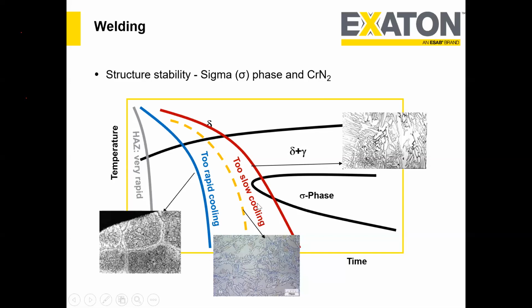For duplex stainless steel, we need to optimize the cooling rate in such a way that it neither intersects the C curves, which form the undesired sigma phase or chi phase, nor cools so fast that it forms chromium nitride. If it forms chromium nitride, see the problem: we are depleting the chromium and also the nitrogen, so our effective pitting resistance is depleting. Hence, that area is a potential site for pitting attack. The sigma phase is exactly the same thing. It is extremely hard, brittle in nature, and a potential site for pitting corrosion. So we need to optimize the parameters in such a way that we get the desired microstructure.